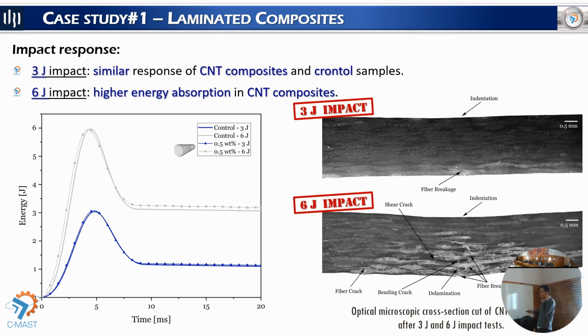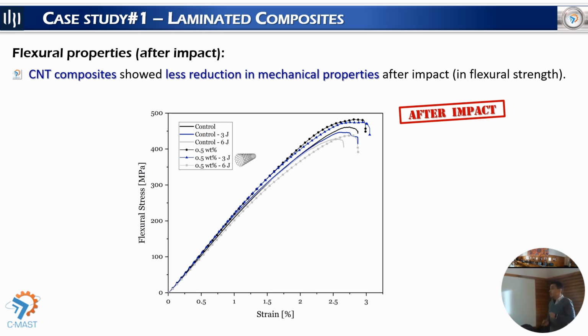We can see fiber breakage, delamination, shear cracks. So this kind of impact really compromises the structure. This is why it is so important to try to monitor this kind of event by piezoresistive means, as I will show you in the next slides. We also studied the influence of the carbon nanotubes in the samples after the impact. And here we can verify that the composite samples with carbon nanotubes present a smaller reduction in the mechanical properties after the impact. Once again, the carbon nanotubes improve the mechanical properties.